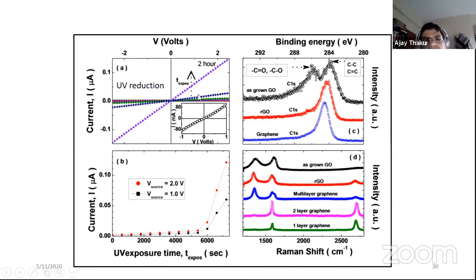reduction via exposing to UV light. So in this case, after making a 4-probe contact, we put it in a controlled environment of UV light illumination. And then as a function of time of UV irradiation, we took IV characteristics systematically. From this data, at the bottom panel is shown how, as a function of time of exposure to UV, the current gradually starts increasing.